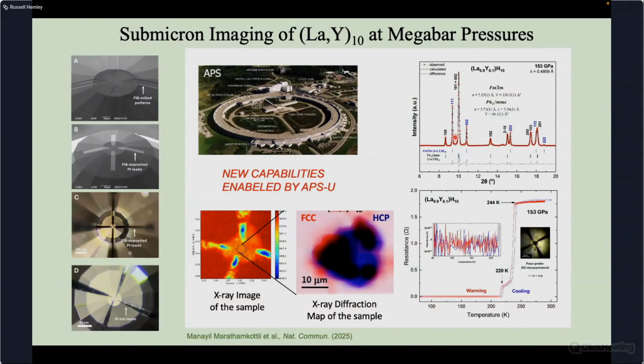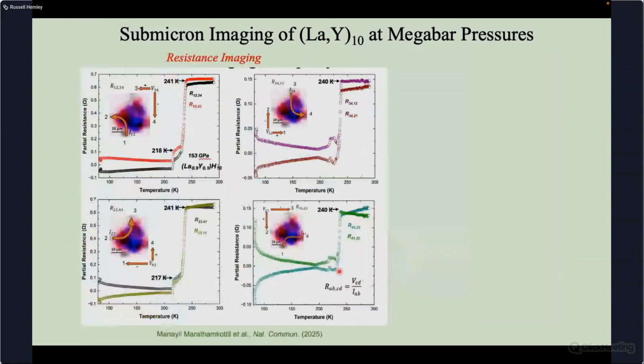And interestingly enough, in this system, we're near a border between the FCC and the HCP structures, and we see 2 superconducting steps, a high TC and a lower TC. The lower TC is still quite high, 220 Kelvin. And the question is, which structure is contributing to which superconducting step? Well, we can actually work that out by mapping out the structure and then correlating that with where we are measuring the resistance in these experiments.